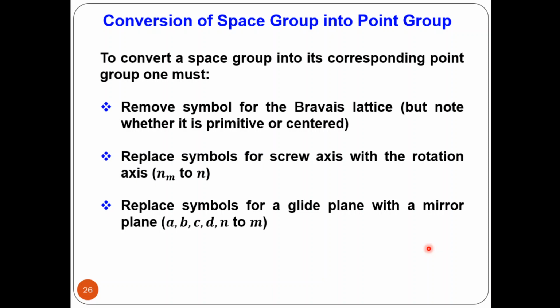Now, how to convert a space group into its corresponding point group? A very simple technique is involved. The first step is we should remove the symbol for the Bravais lattice, but note whether it is primitive or centered. This is just for your note. Just note the Bravais type of that unit cell, and then you should remove it, and then replace symbols for screw axis with the rotation axis: n_m to n. If you have any general symbol like that, then you should immediately ignore this m and consider this n, and then replace symbols for a glide plane with a mirror plane: a, b, c, d, n.